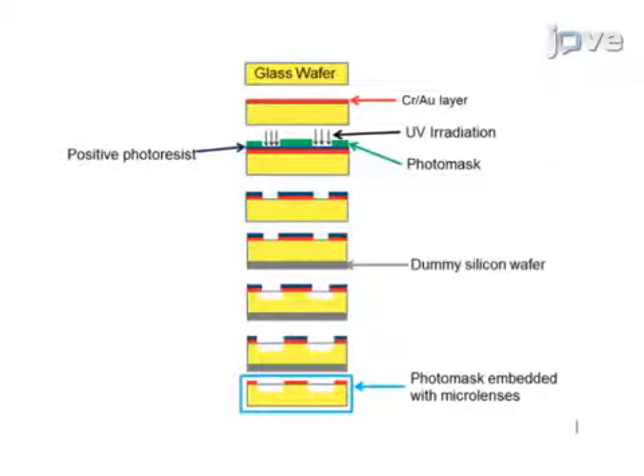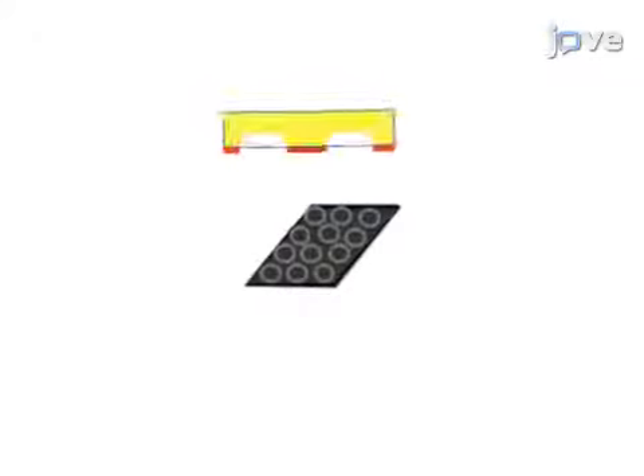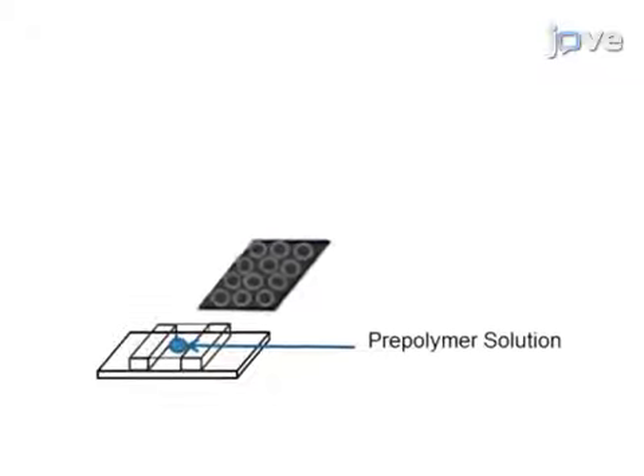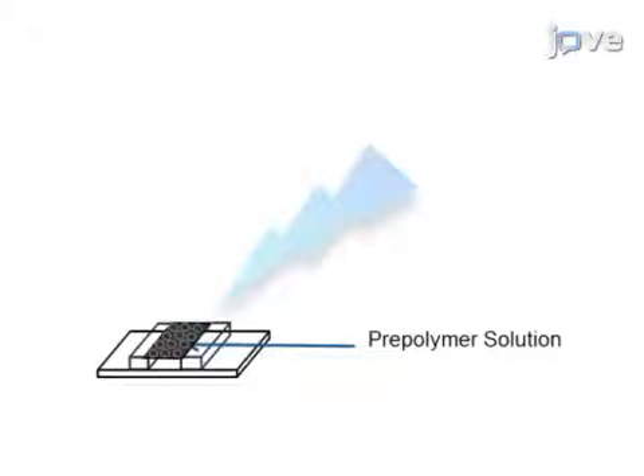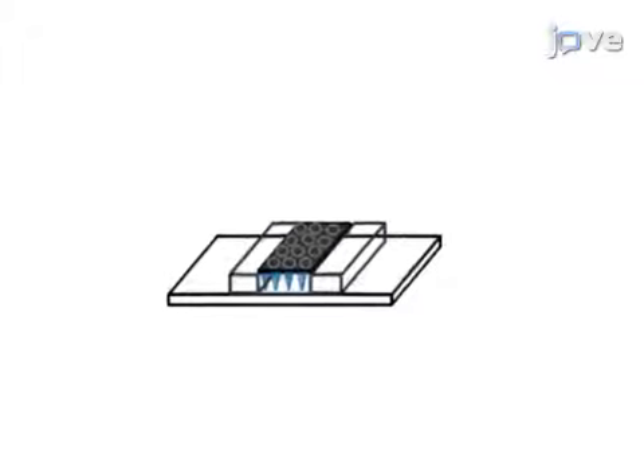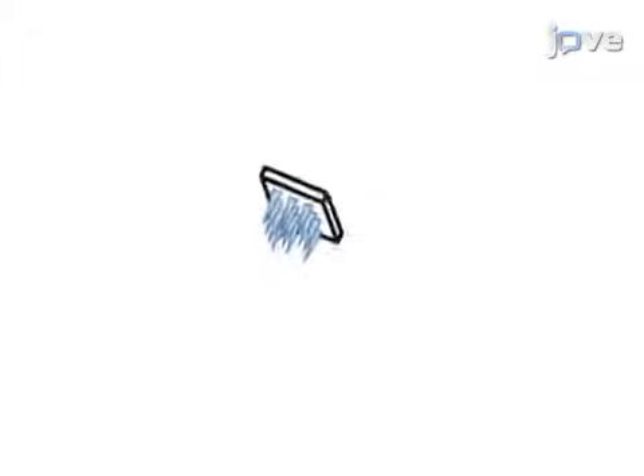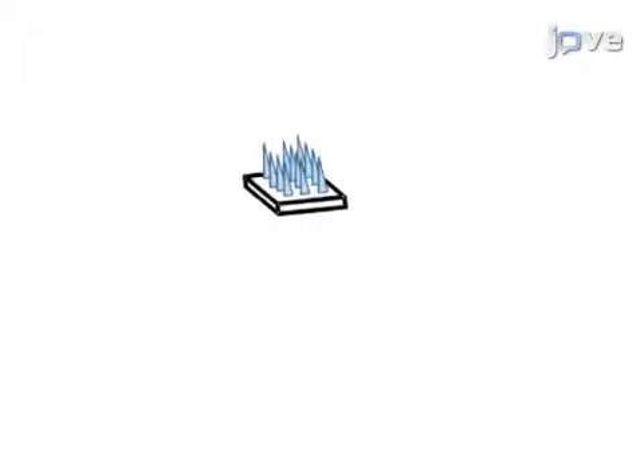This is accomplished by first fabricating a photomask consisting of embedded microlenses via patterned isotropic etching. The second step is to fabricate microneedle shafts by placing the embedded photomask over a bath of pre-polymer solution and focusing UV light into the solution through the microlenses, polymerizing the exposed solution. The final step is to fabricate the backing layer to support the microneedle shafts.